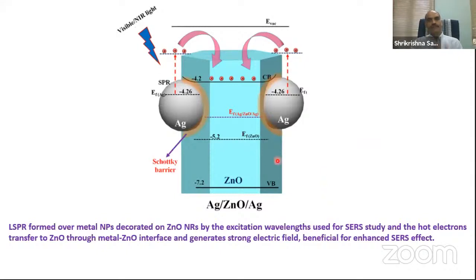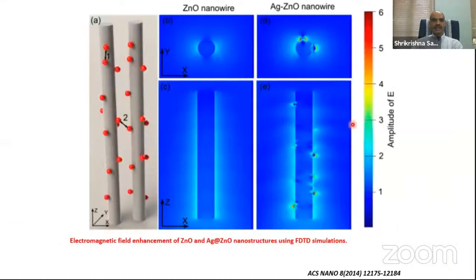So if I want to make it reusable, what I can do is grow these silver nanoparticles on, for example, zinc oxide. Now when you grow silver nanoparticles on zinc oxide, it is useful, because hot electrons are formed. Hot electrons, from the surface plasmon resonance, increase the SERS activity or SERS performance. And then these silver nanoparticles give me higher intensity. You can see, for example, silver nanoparticles grown on zinc oxide nanorods.